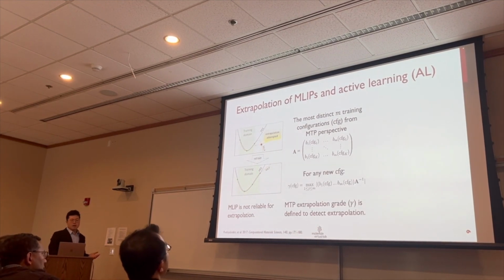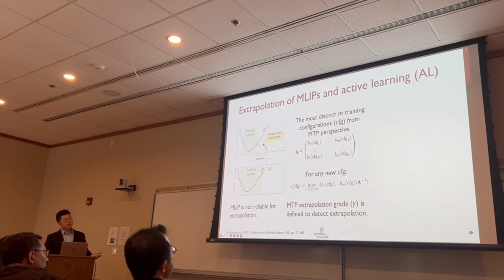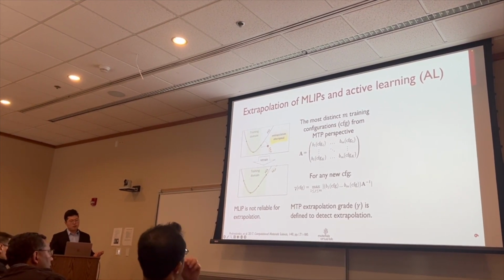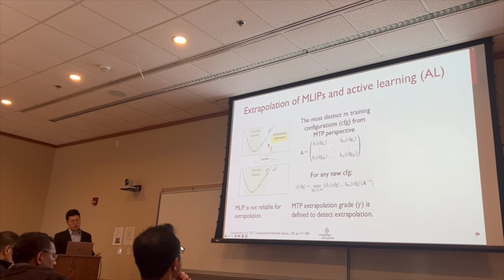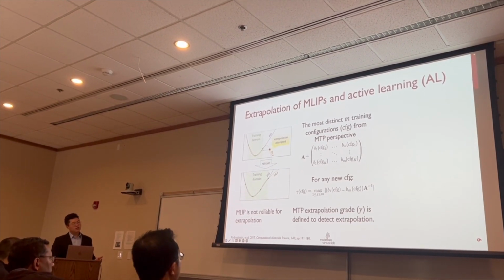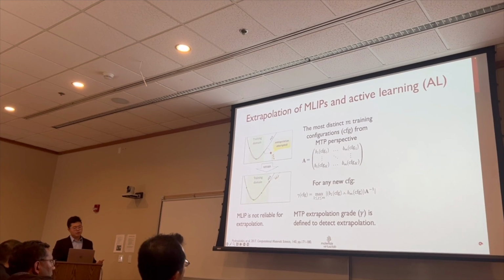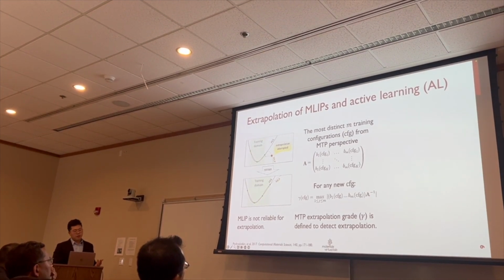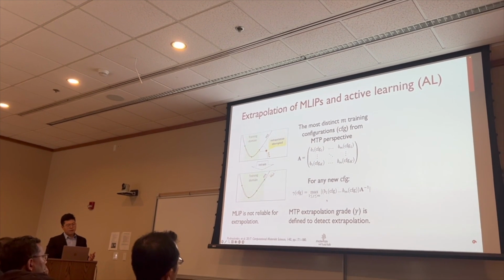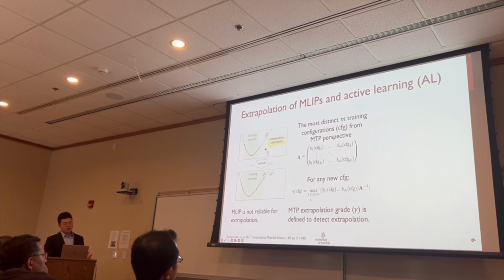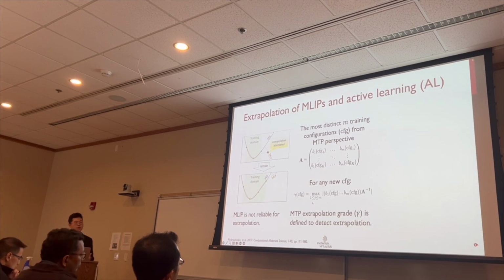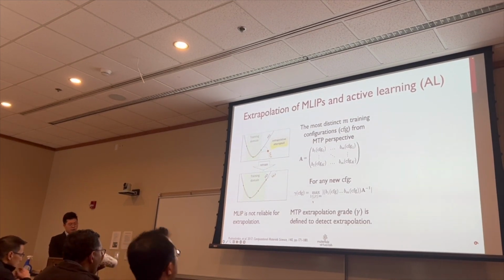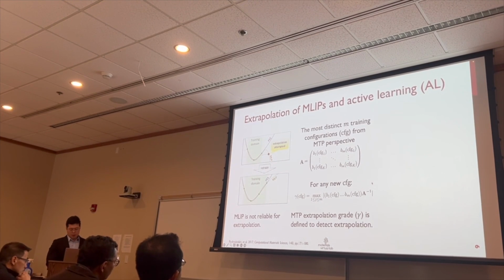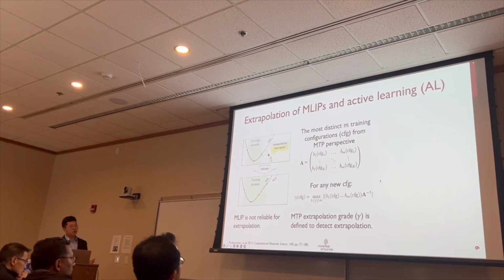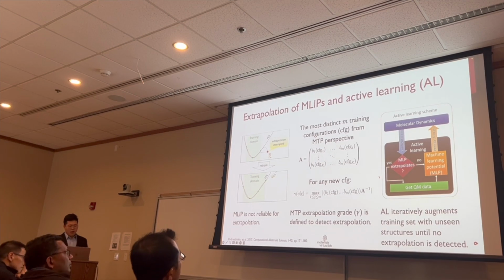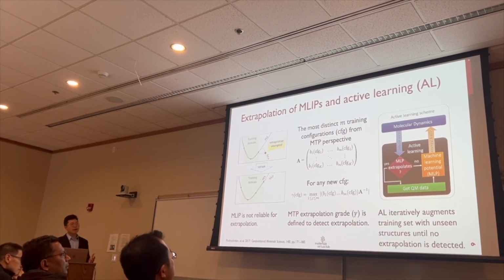So for any new configuration, we calculate this extrapolation grade gamma, which is defined in this way: the maximum value of the feature vector of that configuration times the inverse of the matrix A. If this value is larger than 1, it means that our new configuration is more distinct than some of the existing structures in the training set. So by this rigorous definition of extrapolation behavior, MTP is able to achieve this so-called active learning scheme.